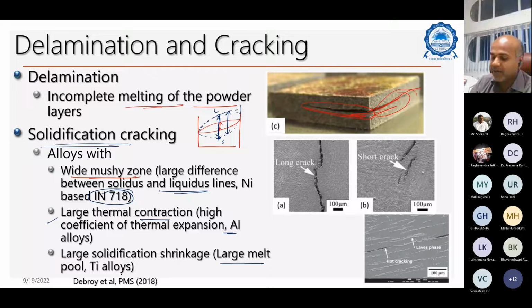Okay, and a large melt pool in titanium, especially large solidification shrinkage like this, for titanium alloys. These are the typical cracks you see: long cracks, short cracks, and these cracks. Okay, these again happen between the layers. Somehow you have to work this out.